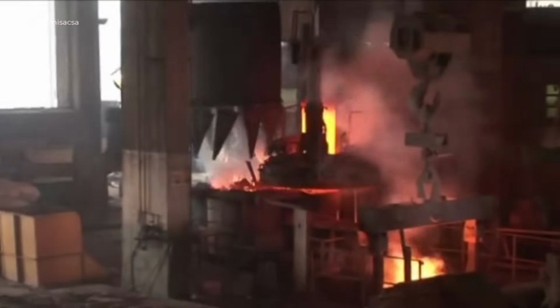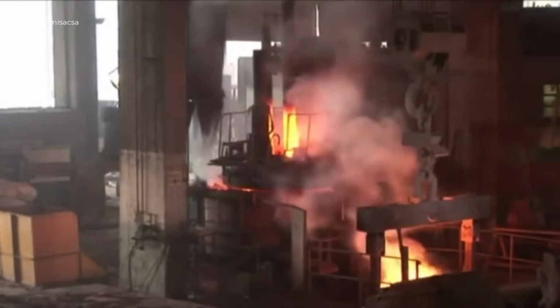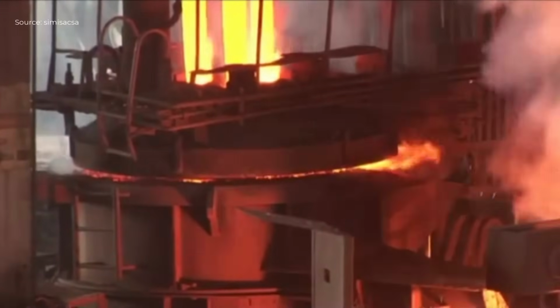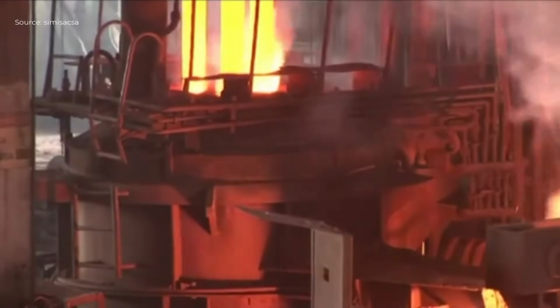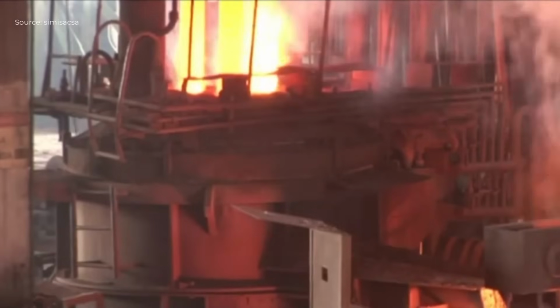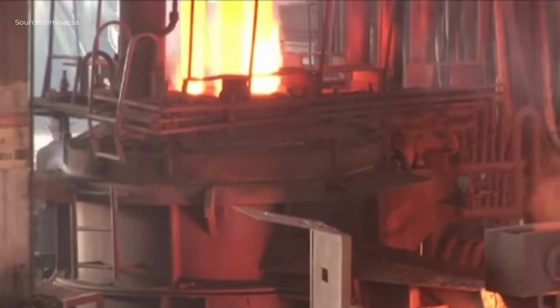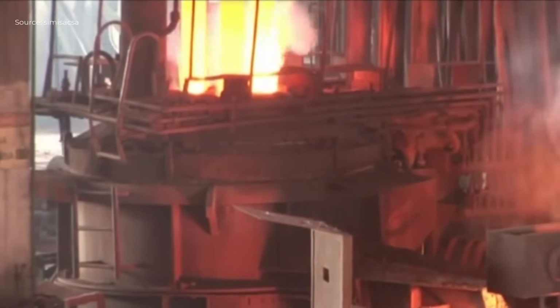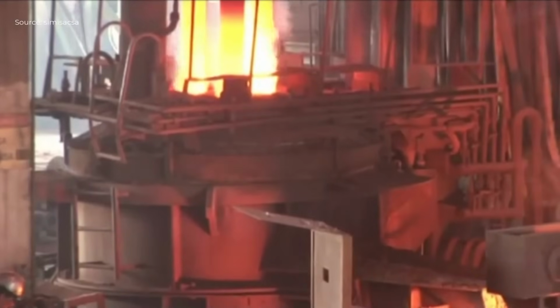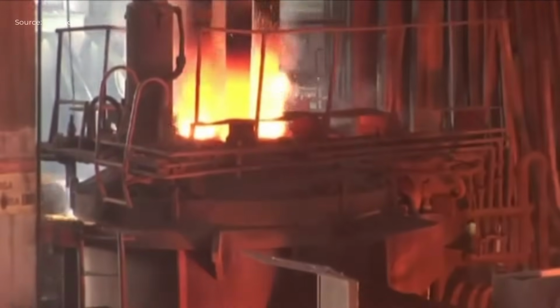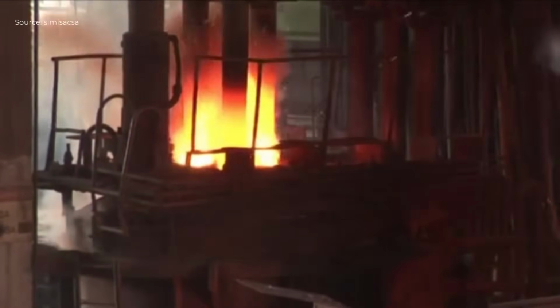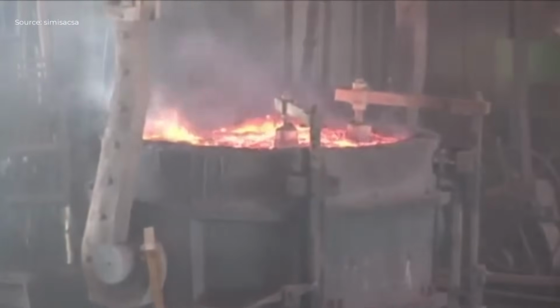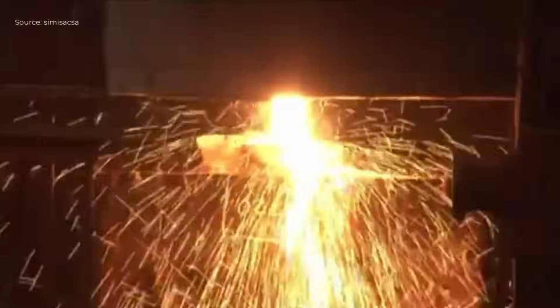Molten metal, such as steel, aluminum, or iron, is prepared in a high-temperature furnace, typically an electric arc or induction furnace, reaching temperatures exceeding 1,500 degrees Celsius for steel. The molten metal is refined to remove impurities, ensuring optimal flow and material properties. It is then transferred via a ladle and poured into the mold through a sprue, a vertical channel connected to runners and gates that distribute the metal evenly, minimizing turbulence and preventing air entrapment.